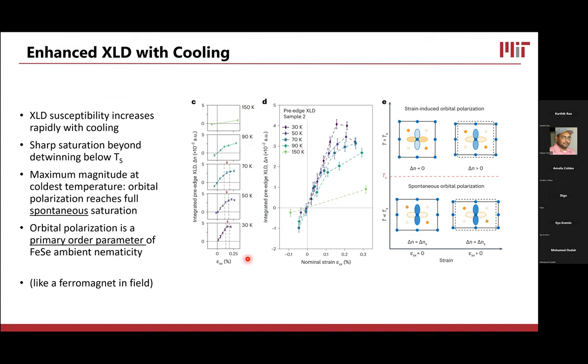Then with cooling below the transition, we can use X-ray linear dichroism and optical birefringence measurements to work out the range where the sample becomes fully detwinned. That's given with these generous-width dotted lines here. This point is showing us where the sample becomes fully detwinned. And again, you see at 50 Kelvin and then again at 30 Kelvin, past the point of full detwinning, the sample is now saturated.